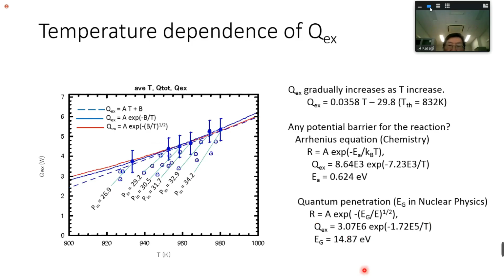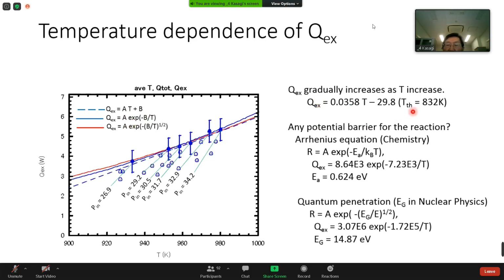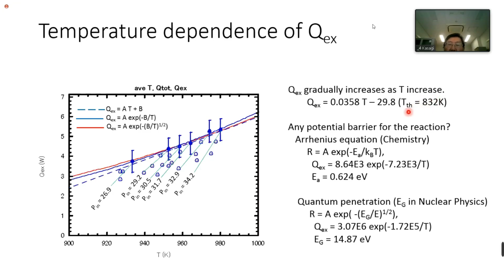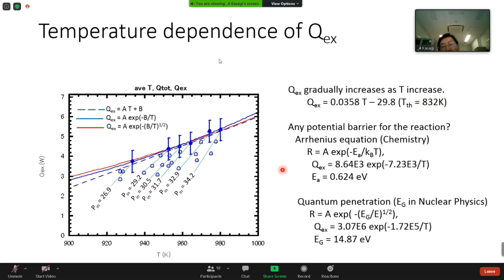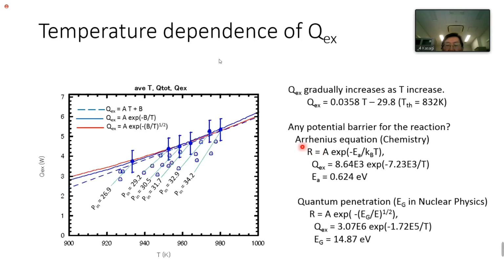Okay, so temperature dependence of excess heat is something like this. If temperature goes up, the excess heat goes up. We put three graphs or three lines over here. This is a simple fit to the data, just a linear fit. From here, if you have a threshold for temperature, the temperature is something like this. But we know that at very low temperature, we also have the excess heat, so this cannot be applied. And many people applied the so-called Arrhenius equation used in chemistry. Then we apply that. That is the blue line. So the activation energy is something like 0.6 electron volt.